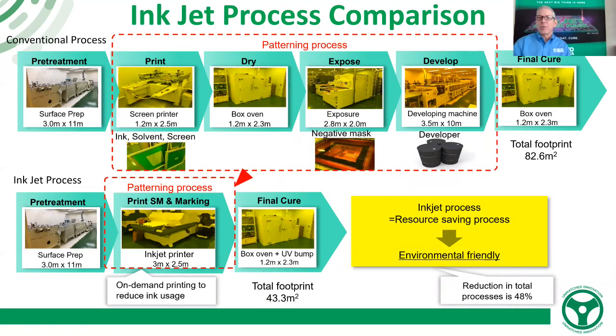So let's quickly go over the processing. So right now, you pre-treat the board, you print the board with your solder mask, you tack dry it in an oven, you expose it with your artwork on an exposing machine, you put it through a developer to develop the unexposed mask off, and you cure the board. With an inkjet process, you pre-treat the board, you print the board, you cure the board. It's really that simple. You're saving steps, you're saving time, you're cutting down your footprint, you're cutting down on people, you're cutting costs. You're cutting costs and improving yields. That sounds like a win-win situation.